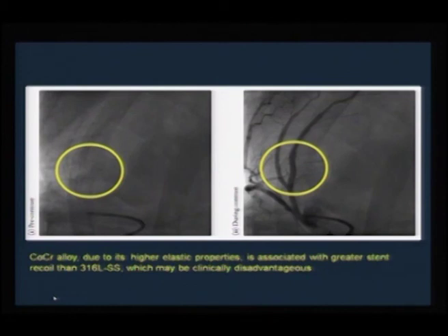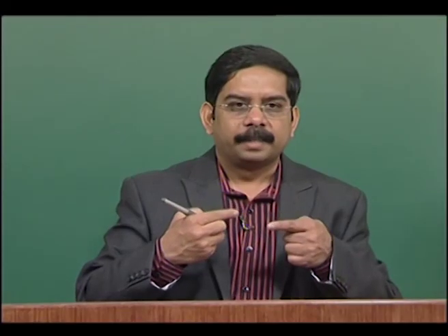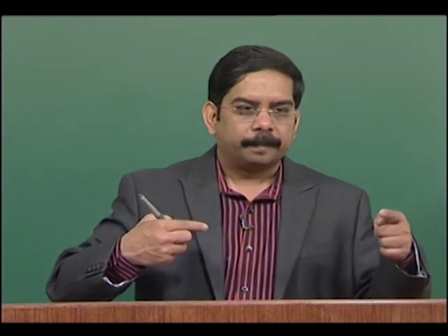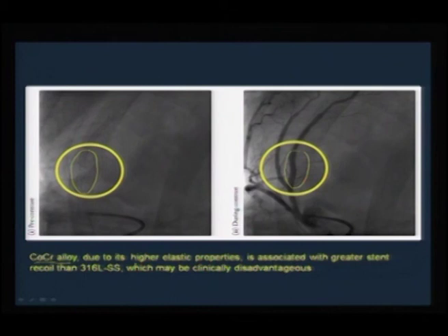Here is another example where you can see the visibility factor. You can see the stent is placed here, and you can see the visibility of the stent very clearly. Why it is important is this is done in the branching area, therefore it is very sensitive that it should not rupture this junction. So, the choice of your stent is very important. In other words, you have to use a thin strut instead of a thick strut, otherwise it will induce more loading at this interface, which may be detrimental for the patient. Also it is found that cobalt chromium alloy, although it has higher elastic properties and is associated with greater recoil strength, is because of its recoil property clinically a bit disadvantageous when you compare to 316L stainless steel stent.